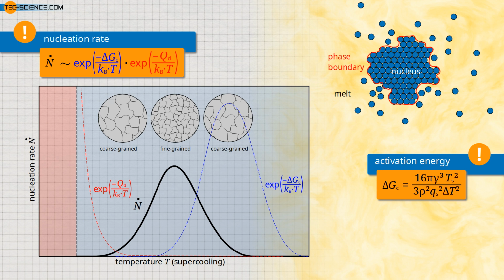However, the diagram also shows that excessive supercooling can even completely suppress nucleation. Such a strongly supercooled melt then solidifies without crystallization. The particles are frozen, so to speak, before they could form a crystal structure. We then speak of amorphous metals or metallic glasses. Amorphous metals are characterized by extremely high hardness and strength and are limited to a few specialized applications due to the costly manufacturing process. High-end golf clubs, for example, are made of metallic glass.